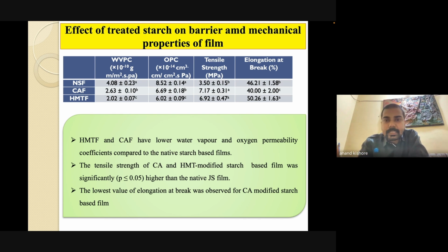In the case of tensile strength, it increases after modification. But for elongation at break, you can see that after heat moisture treatment, the elongation at break increases. But in the case of citric acid, it decreases. In a packaging film, the tensile strength should be high and the elongation at break should be high. But in the case of citric acid, the value is less. So it may be that we developed cross-linking, which reduces the mobility of the molecules in the structure of the starch. That's why the elongation at break is reduced if we compare with the HMT.